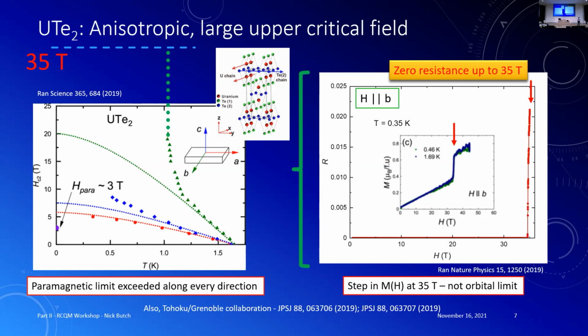So point number one is these are large, anisotropic, and the paramagnetic limit, the Pauli limit, is exceeded in every direction. So this has to be a spin triplet or a really weird spin singlet, but I'd say spin triplet. And now the second thing is that when you're looking along the B direction, you get at some point around 35 Tesla back into the normal state, okay? But this is accompanied by a jump in the magnetization, and we'll come back to this later.